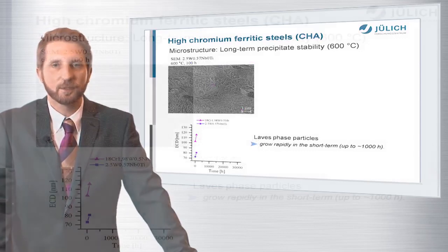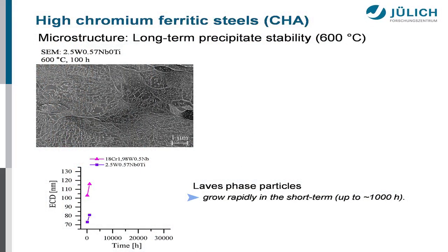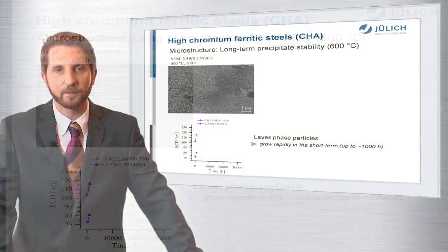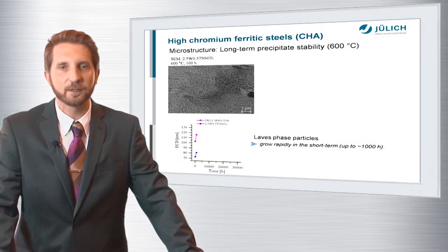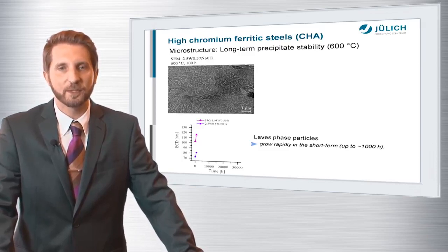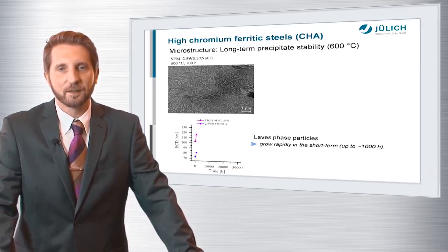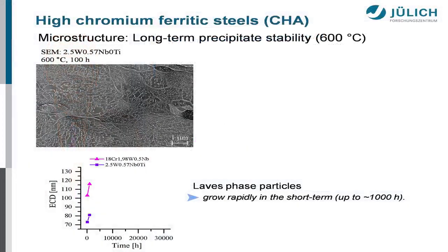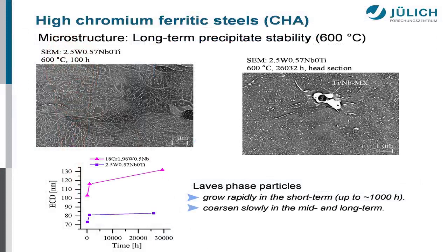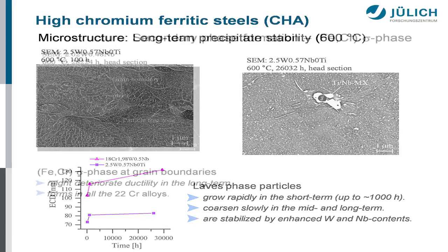Some words on microstructure and particle stability. The micrograph you can see here was taken after comparatively short time annealing of 100 hours at 600 degrees C from the 2.5 tungsten alloy. And you see a multitude of very small particles, and the graph beneath it shows that the growth of these particles is quite rapid during the first 1,000 hours, but in the long term, these particles coarsen very slowly, which is quite nicely depicted in the micrograph taken after approximately 26,000 hours on the upper right. So the particles are really stable.